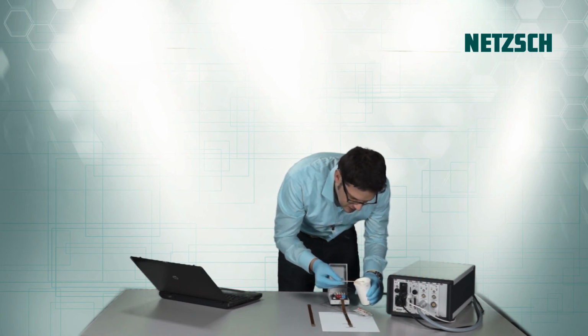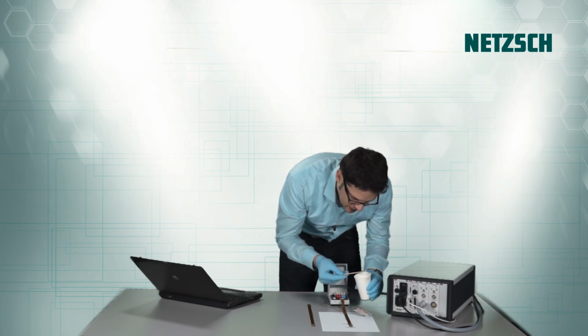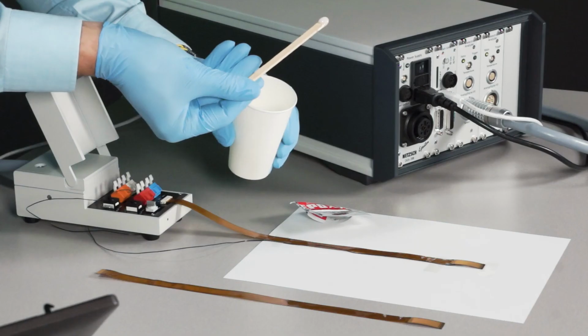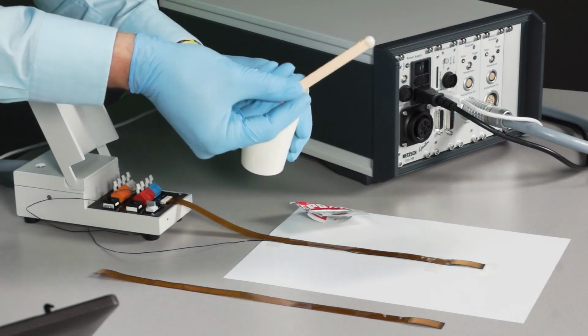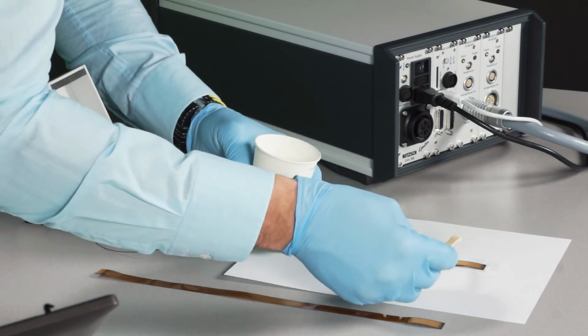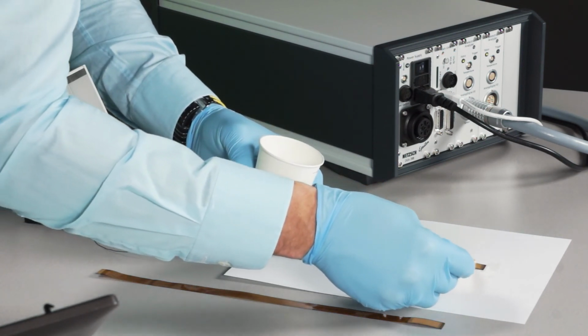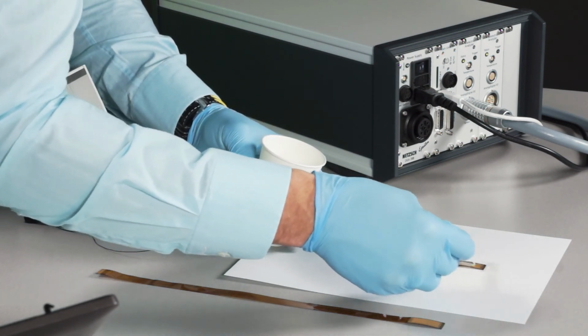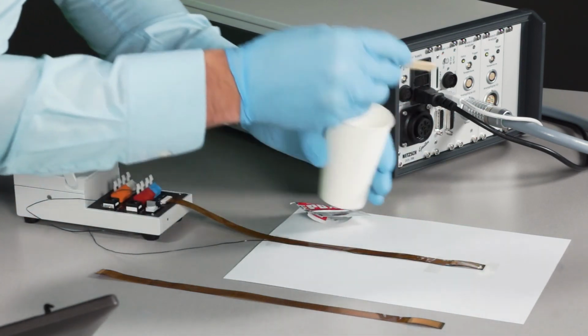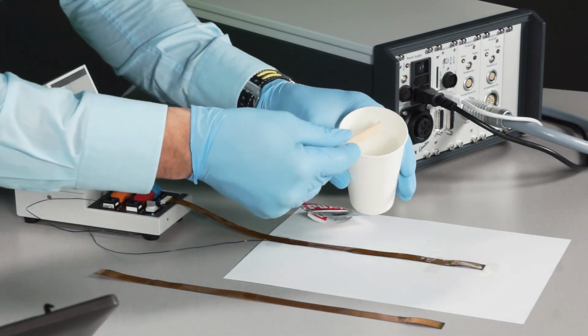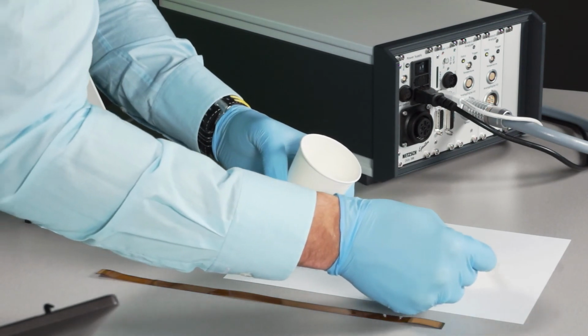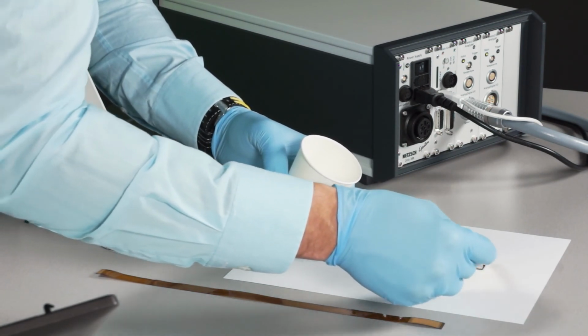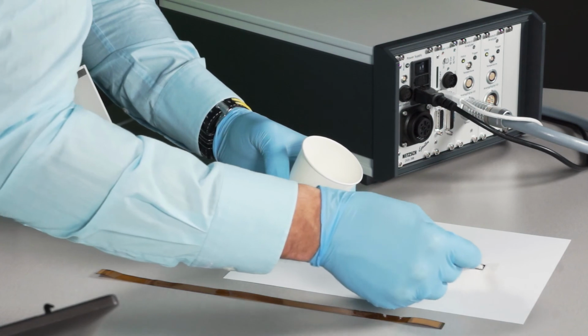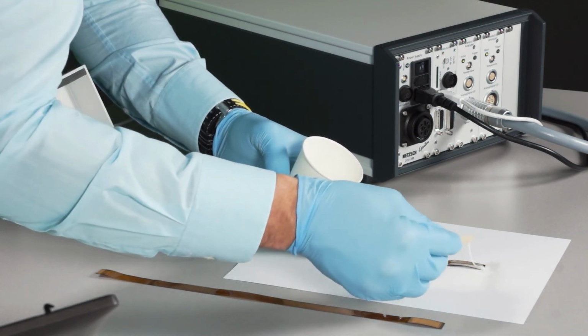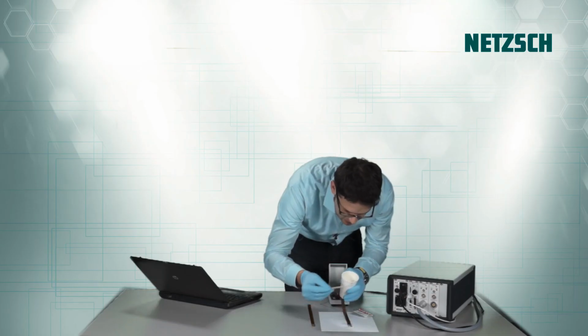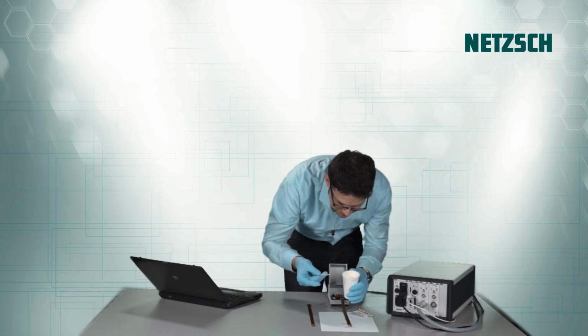Then I use this wooden spatula to apply the resin onto the sensor. In this case, it is important that you coat the whole sensor with the resin. So all the electrodes should be coated, and you should take care that the thickness of the resin is homogeneous.